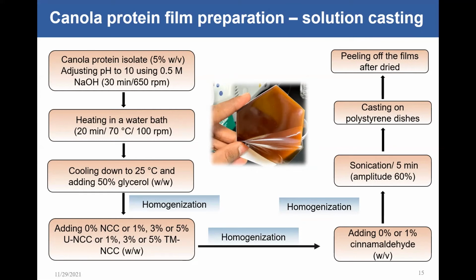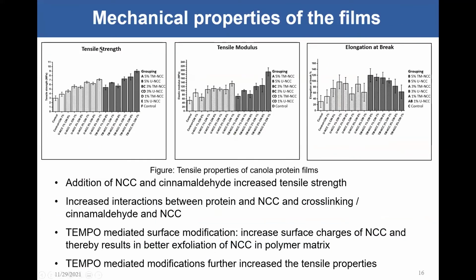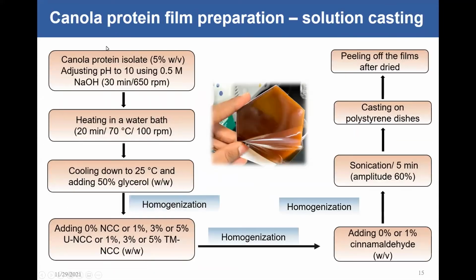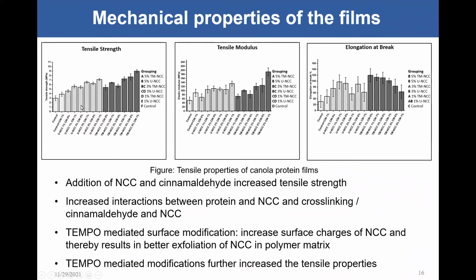So once the film casting is done, one of the primary things is we need to characterize their film properties. There are three main mechanical properties that we need to look at. One of them is the tensile strength. The other one is tensile or elastic modulus. And the third property is elongation at break. With the tensile strength, as you can see in here, compared to the control canola film, which is basically the canola protein without any nanomaterials, either modified or unmodified, your tensile strength is around 3 megapascal for the packaging film. That's the unmodified canola film.